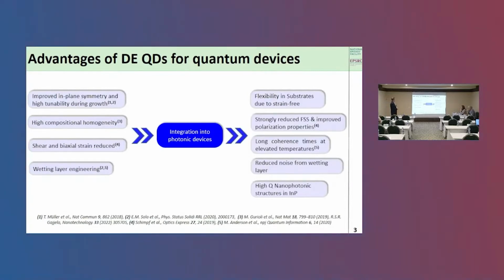So there are a number of interesting properties of droplet epitaxy that make it useful for devices. Because it doesn't rely on strain, we have reduced in-plane asymmetry, so you have high symmetry in the dots. We have very good compositional homogeneity. These are almost pure indium arsenide quantum dots, which can be challenging in the Stranski-Krastanov method. And we have no shear and biaxial strain associated with the lack of a strain-driven process and the wetting layer engineering I mentioned. That means that we have flexibility in what substrates we want to use, the strain-free aspect.